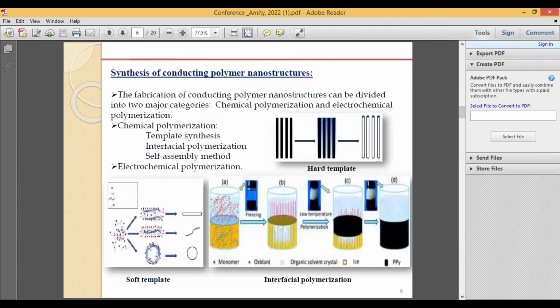Then there are different synthesis mechanisms to synthesize different nanostructures. There are basically two major categories: one is the chemical polymerization technique, and the other is the electrochemical polymerization technique. Here we have followed the chemical polymerization technique, using the self-assembly method. Although synthesis of nanostructures by the template method is very good, meaning we can synthesize very well-ordered nanostructures, there is a major drawback: we need to remove the template after synthesis of the nanostructure, so there may be a chance of destruction of the nanostructure. That's why we have followed the self-assembly method. Here, the dopant we used serves as a micelle and guides the formation of the nanostructure.